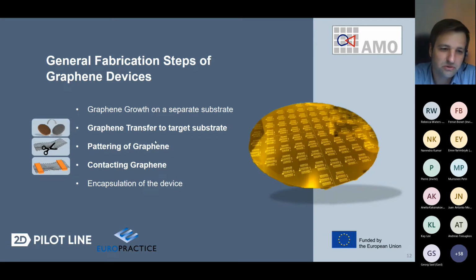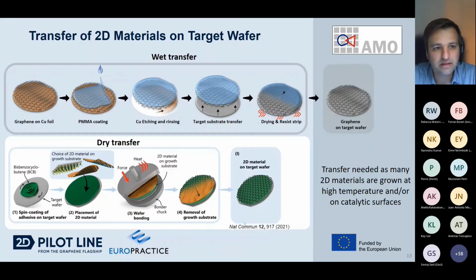And I would like to talk a little bit about these three things here in the middle: the transfer, the patterning and the contact of the graphene, as these are important steps during the fabrication. The transfer of 2D materials is necessary as they are mostly grown on different substrates due to high temperature or because catalytic surfaces are needed. And these are not always compatible with the targeted wafer, where you may have to process in CMOS conditions. So there is a need for transferring these materials.